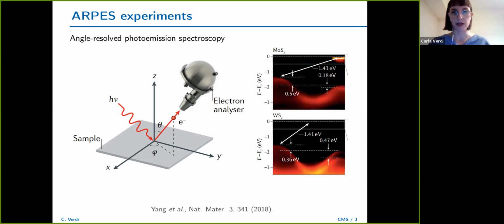This is of course well known and very old, but the progress that has been made by experimentalists in this field in the last 10, 20 years is really, really impressive. So for example, this is the band structure of some transition metal chalcogenide. And you see here, it's particularly shown the region of energies near the band gap. But what is really impressive is that nowadays experimentalists can reach a level of resolution that was really unimaginable years ago. And so what people can do is to really probe the many-body physics in the materials. So you can probe all sorts of many-body interactions. So of course, electron correlations, but also the interaction of electrons with phonons.